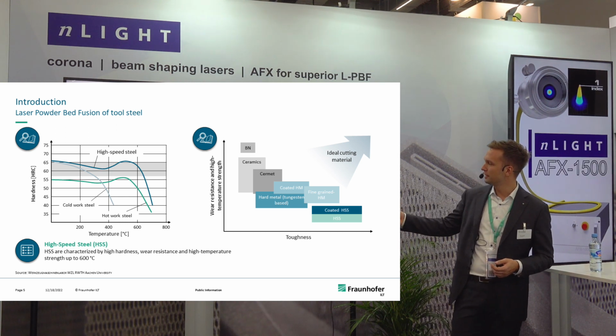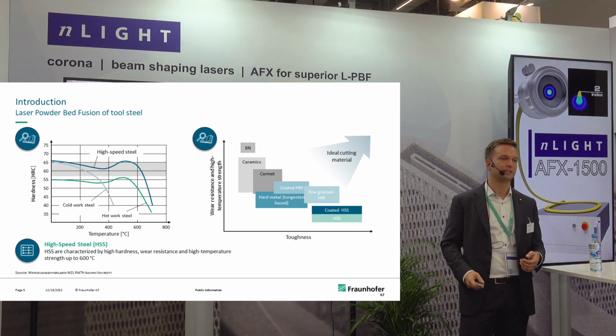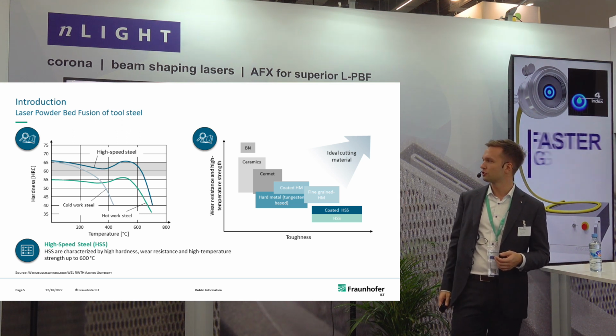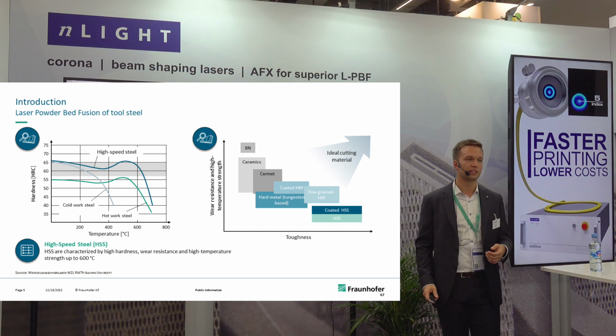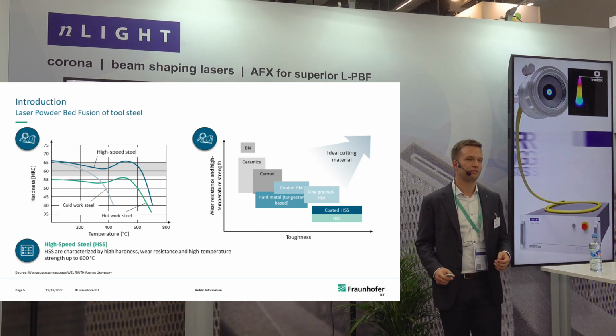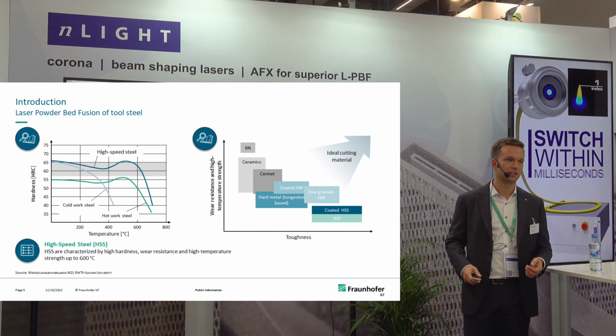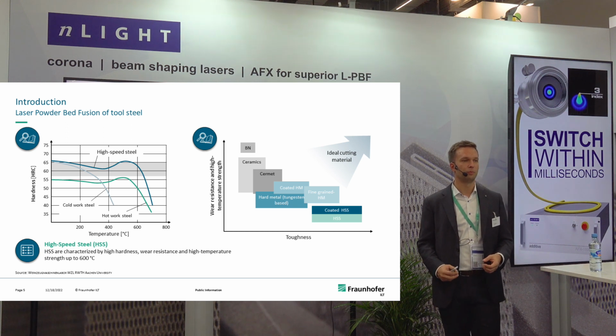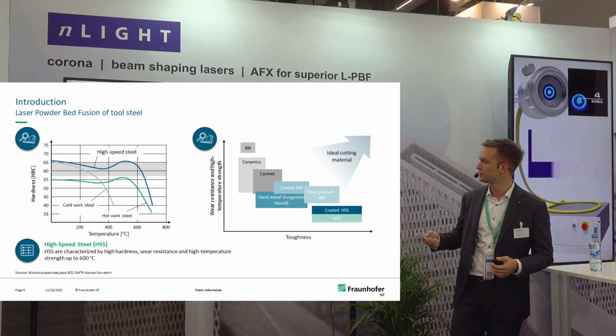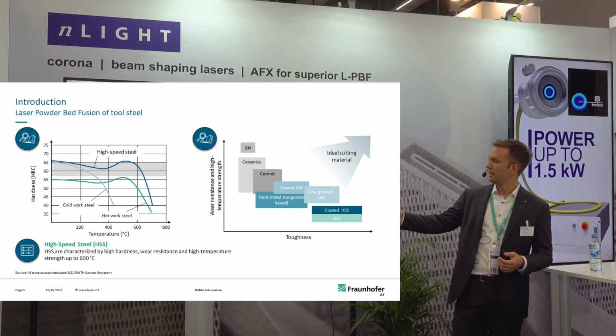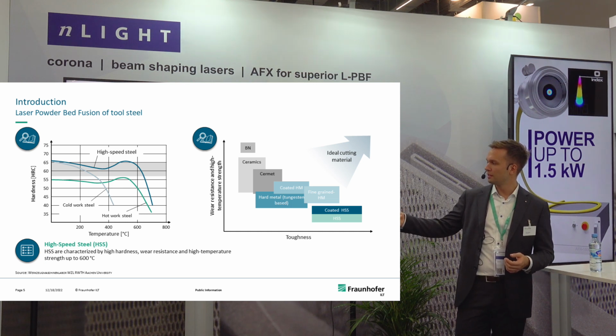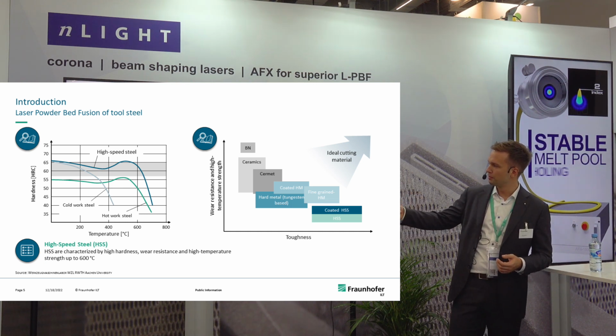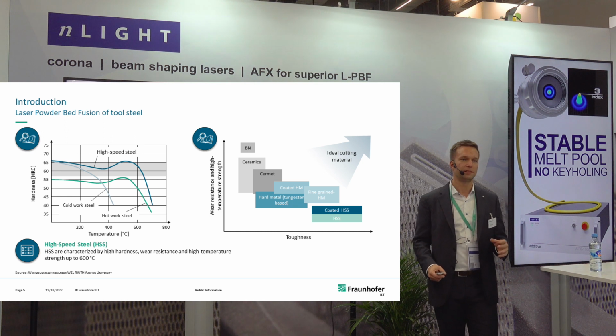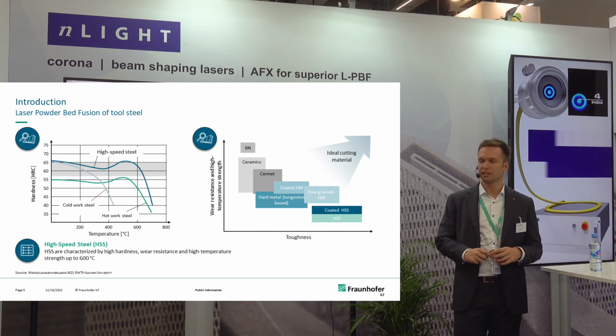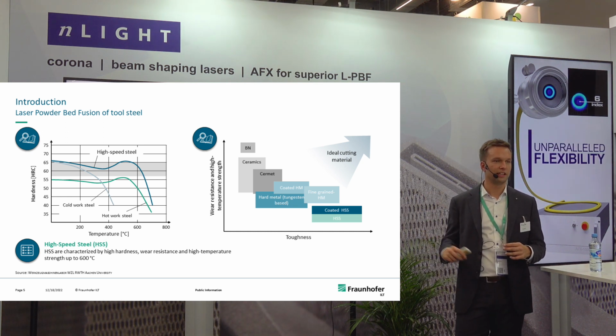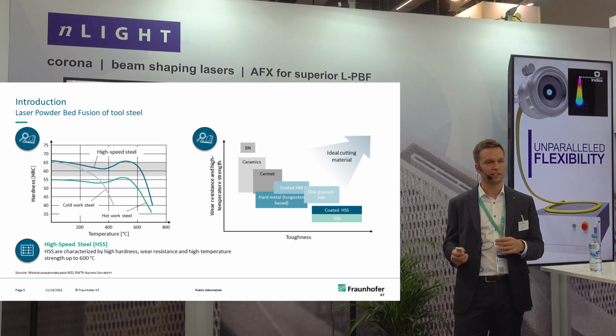What is actually quite interesting is the high-speed steels that are also shown in the curve. Those are not as hard, but have fairly good impact toughness, for example, so that they are a bit more ductile in terms of the applications. So to give a short summary of the material we are targeting, high-speed steel, very good hardness, especially at elevated temperatures up to 600 degrees C.